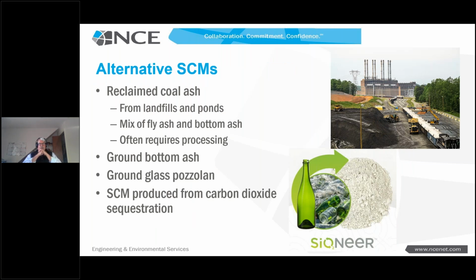These days, there's a lot of interest in alternative SCMs. ASTM C618 is starting to expand its definition of what is going to be an acceptable pozzolan for use in concrete. Reclaimed ash that's mined from landfills or ponds is one really major source of potential pozzolan, and this is already being done. We often have to process this. We have to dry it. We have to burn out some carbon on occasion. We have to do some grinding to make it work, but it seems to work well. More uses are being considered for ground bottom ash and ground glass, and then there are some specially prepared pozzolans being looked at that are even sequestering CO2 in the process. All of these are being investigated and more are being sought.